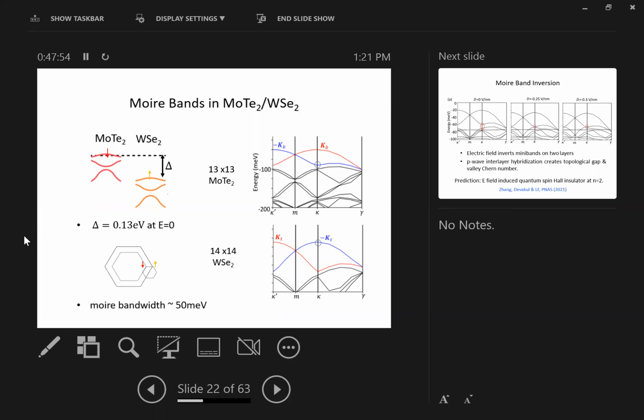So okay, in this system, MoTe2/WSe2, again, there's a band offset, but this band offset is much smaller. It's only 0.13 eV at zero electric field. So as we apply electric field, this delta can be further reduced. So this tunable charge transfer energy is key to the phase diagram.